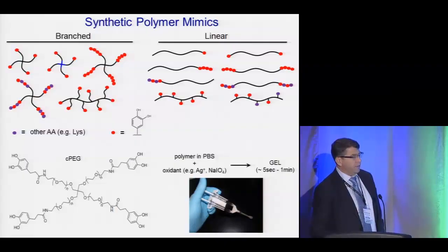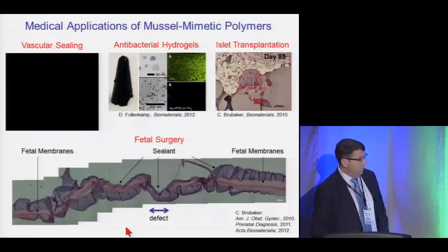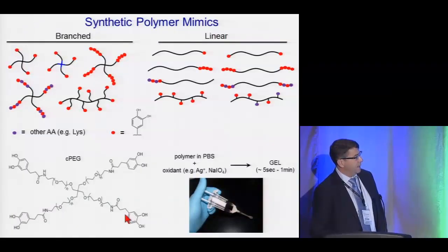And it's a fairly simple construct. Not fairly simple, it's very simple. It's a branched polyethylene glycol with catechol end groups. Not even a dopa on the end group, it's just the catechol. And I would point out also that the concentration of the catechol in this polymer is much, much lower than in most of the mussel adhesive proteins.